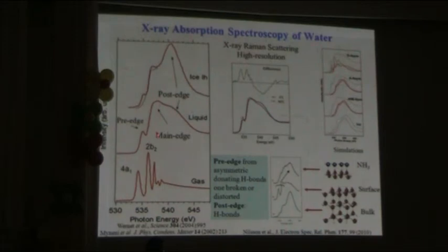This is the X-ray absorption spectrum of liquid water. This is the spectrum of ice. So they're very different. So in the liquid, we lose basically the tetrahedral signal that we see in ice. We get a new sharp feature here that we call the pre-edge. And we get this main edge, which becomes very strong. This is ambient temperature, room temperature. But here's a comparison between 4 degrees and 90 degrees. So the differences are small.